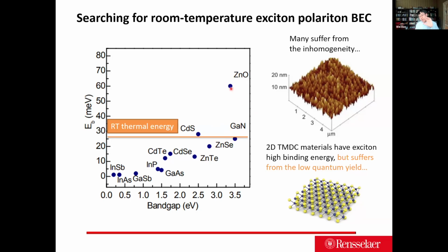And many of the materials with exciton binding energy above room temperature thermal fluctuation, for example gallium nitride and zinc oxide, suffer from inhomogeneities in the material growth. That means the DBR or the materials themselves have much poorer quality compared with the traditional gallium arsenide or cadmium telluride. And many of the emerging materials, for example the one that I used to work with, the TMDC materials, have excitons with really high binding energy, but they suffer from low quantum yield compared with gallium arsenide. So many materials have been tried to realize the ultimate dream of room temperature exciton-polariton BEC, but they all have certain limitations.